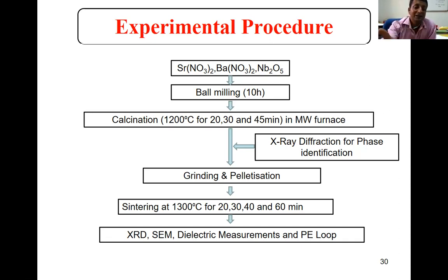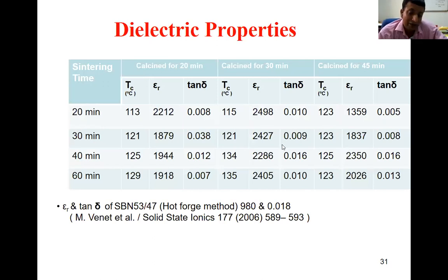This heat is released in the exothermic process, and the microwave is absorbed by our specimen. So the heat supplied to the specimen will be magnified, and the sintering process will be fast, which we call reactive sintering. So what becomes a disadvantage in the conventional process becomes an advantage in microwave processing. We tried it and got better properties compared to the calcined powder which was in single phase form. This is reactive sintering: the reaction is also taking place, and sintering means the grain growth also takes place.